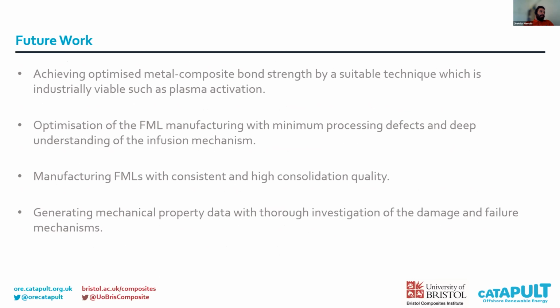Regarding the future work, some of these tasks have already been achieved through different publications that we have at the moment. So, achieving an optimized metal composite bond strength by a suitable technique which is industrially viable, such as plasma activation. Optimization of the FML manufacturing with minimum processing defects and a deep understanding of the infusion mechanism. Also manufacturing FMLs with high consolidation quality and consistency, and generating mechanical property data with a thorough investigation of the damage and failure mechanisms of these manufactured FMLs.